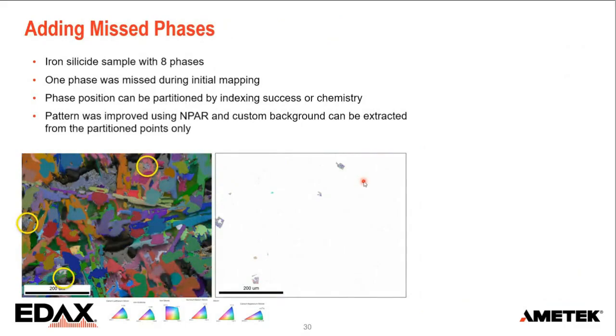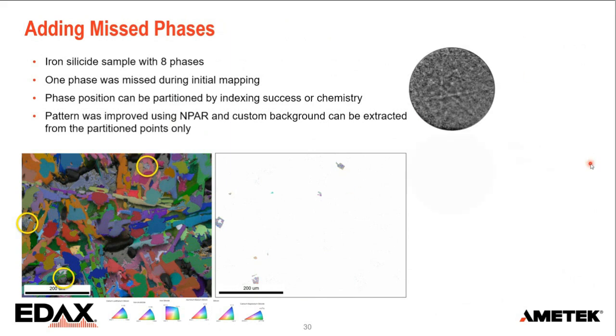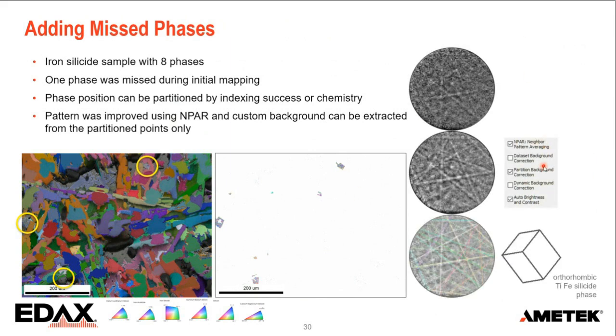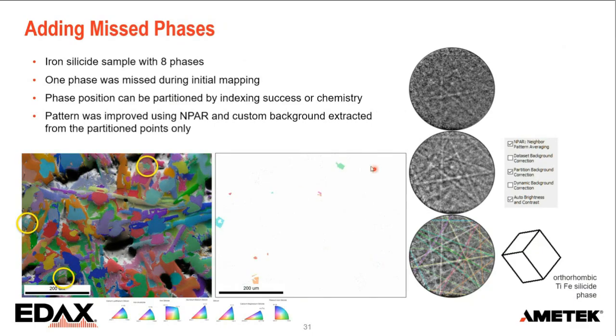Now, here's another one with a missed phase. This is an iron silicide sample. I've got 6 phases already used for indexing. And again, after indexing, I noticed there are a few grains that look okay and are completely speckled. So that indexing went totally wrong. I could identify those by the confidence index, and in this case, also chemistry. So I pulled these out, look at the patterns, optimize that, and identify what it is. In this case, it was a titanium iron silicide phase. I know what it is, then I can just re-index those points, nothing else. And then I can fold that back into the original data set. So now I've got a 7-phase map.